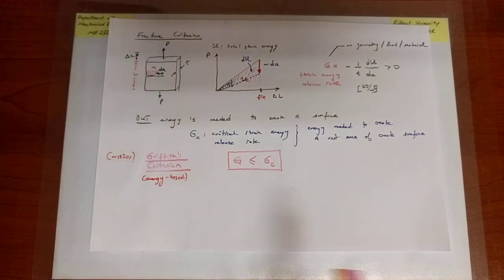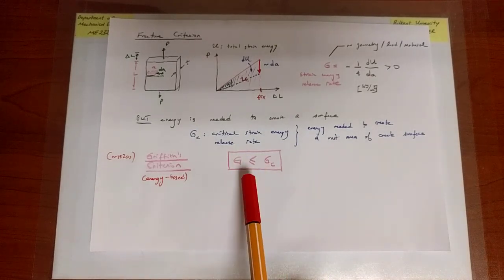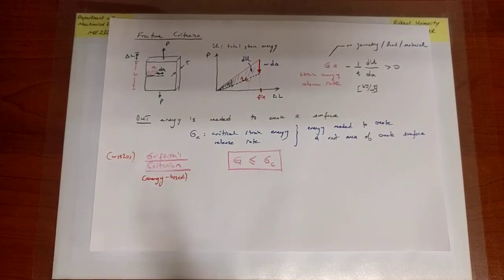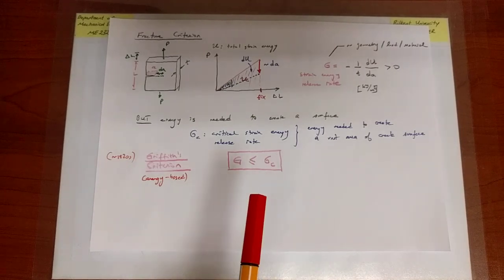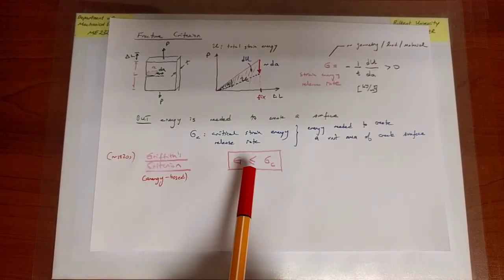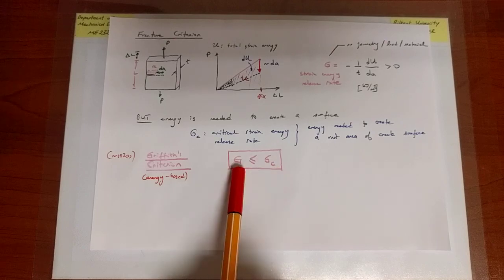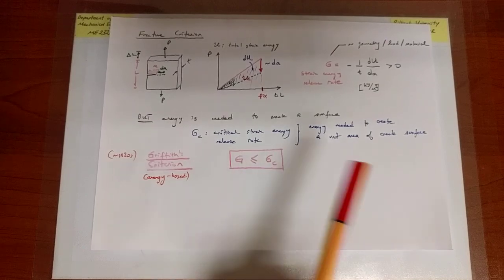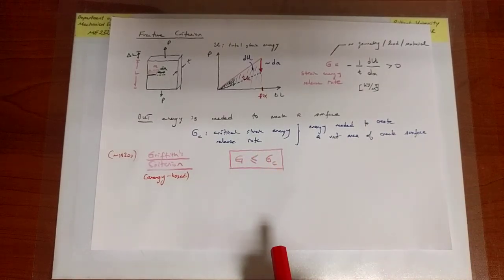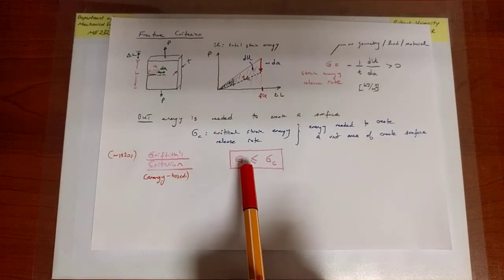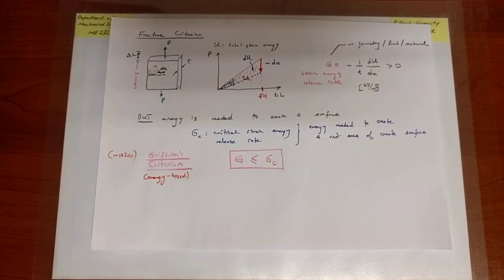So now we are understanding really quantitatively what is happening in the simple peeling experiment that we did. And we have observed indeed that there was a critical point reached when G is equal to GC in my experiment, when the tape started to peel off and the energy that was being released from the system was always sufficient to keep the tape peeling off, the crack propagating towards ultimate failure.